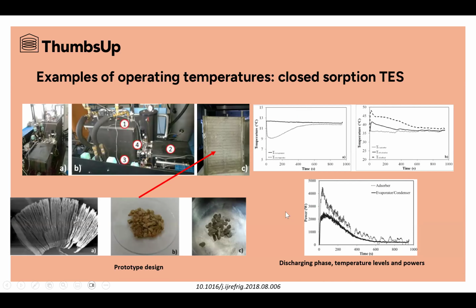This is another example. In this case, it is a closed sorption TES. And just to see the range of temperature, this is the temperature of the evaporator, where this line is the inlet temperature of the evaporator, more or less 12 Celsius degrees, and the dotted line is the temperature out of the evaporator. Here we have the temperature of the absorber. The range of temperature of this application is between more or less 45 degrees and 55 degrees.